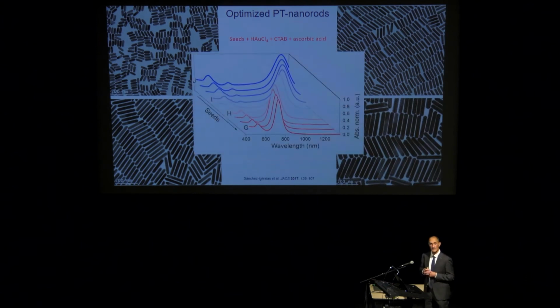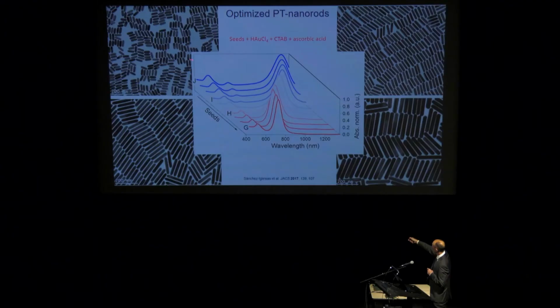Almost no spheres present in the system, and also really tight tunability in the aspect ratio, so you can see the gradual shift of the plasmon resonance. This other resonance goes across the particles, not really affected by the particle elongation. And also in the longer ones, you see another band which corresponds to quadrupolar resonances.